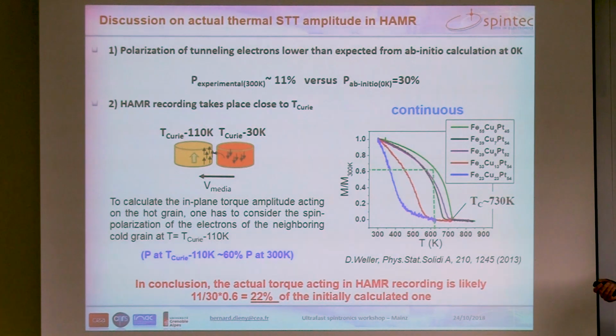So of course, we must not consider the magnetization at room temperature, but the magnetization at 100 Kelvin below TC. But this is 60% of the magnetization at room temperature. So it means that in the simulation that we are going to perform, we have to take this factor 3 here, plus the factor 60% here, if we want to take the proper value of the spin transfer torque amplitude that we are going to plug in the micromagnetic simulation. So if I look at these two factors, the actual spin transfer torque that we have to plug in the micromagnetic simulation is 22% of the spin transfer torque that we calculated in the previous part of the presentation.